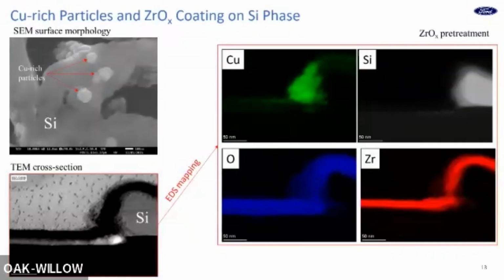This is a high magnification of the precipitates on the silicon particle. Here is 100 nanometers. You can see these are kind of round copper-rich particles. Normally you see this a lot in the aluminum body sheet or extrusion, but here you see this on the silicon. But how did the copper form on the silicon phase? Is it a chemical reduction, or just some hydroxide precipitates? This is something very interesting, and we also got a chance to look at the cross-section of this particle. You see, it's not just on the surface. Actually, it can directly deposit on the silicon. So this is one thing.